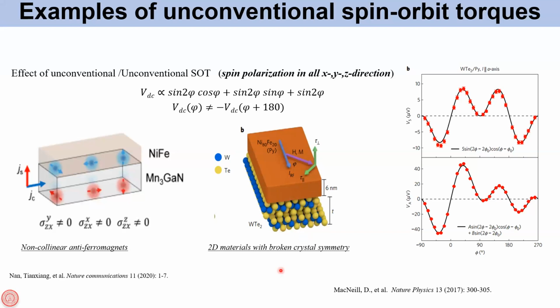In this example, back in 2017, they used the broken crystal symmetry of WTe2 to show that there is an unconventional spin orbit torque. You see here in this STFMR data that the sin 2phi cos phi dependence is no longer there. They saw it in the case of the antisymmetric component. There is an additional unconventional torque present in the system because of the broken crystal symmetry.